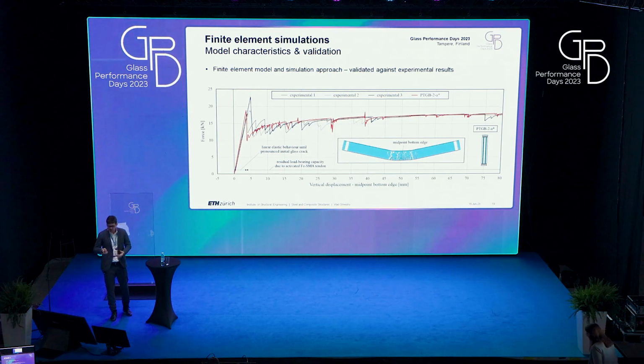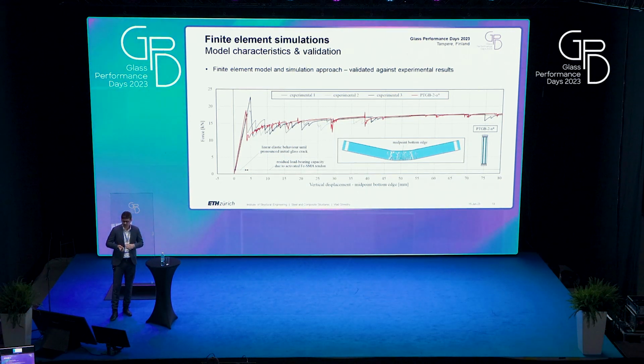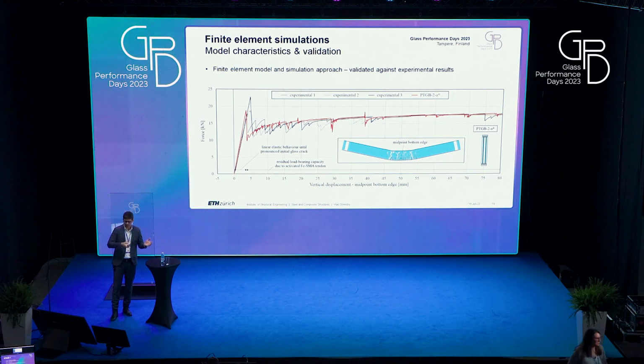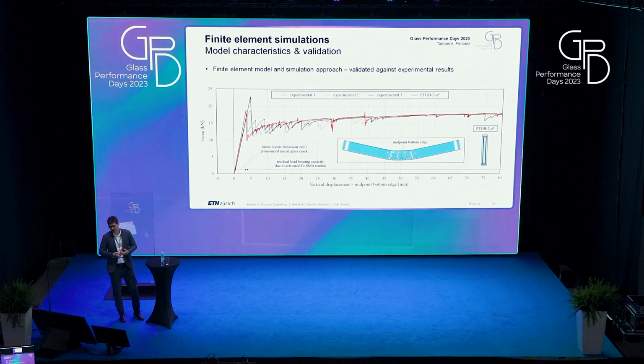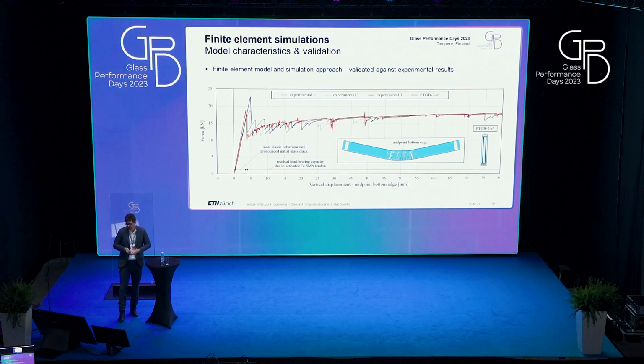With this model, we were able to predict quite well the results we observed from the tests. So we see, before the initial crack, a good prediction, but also the post-cracking behavior was predicted quite well, including the occurring cracks.